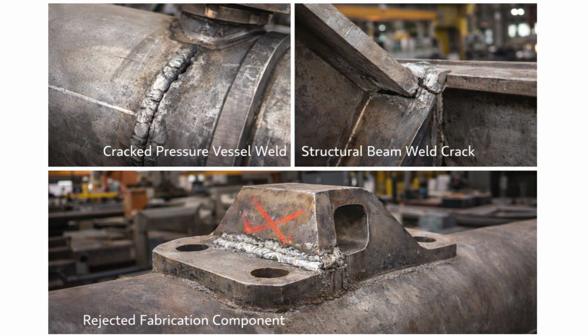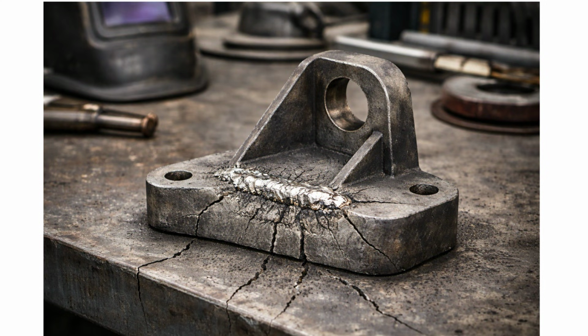What happens if preheating is ignored? Let's be very clear here. Ignoring preheating can lead to cold cracking after welding, cracks in weld metal, cracks in HAZ, repair welding, rejection by inspector, loss of customer trust. I've seen pressure vessel shells cracked overnight. I've seen crane components fail load tests. And in many cases, the root cause was no preheat.